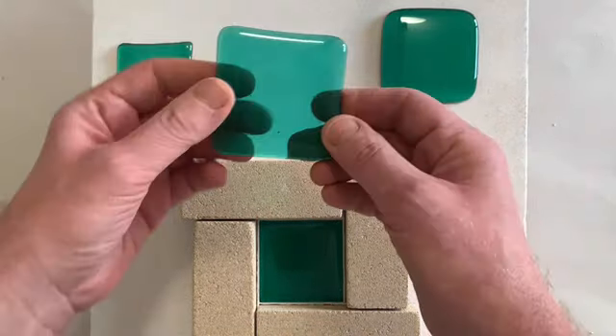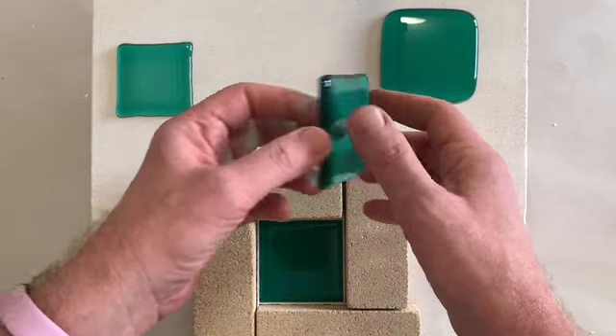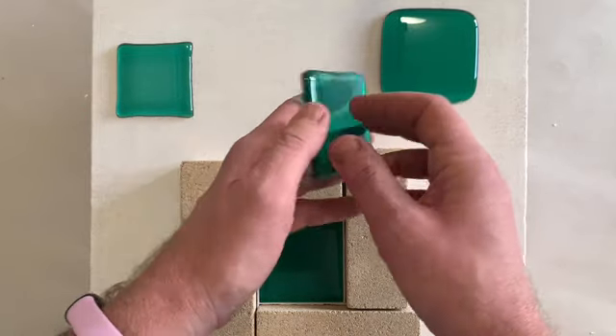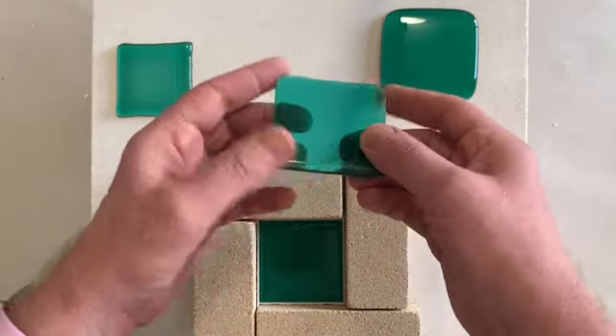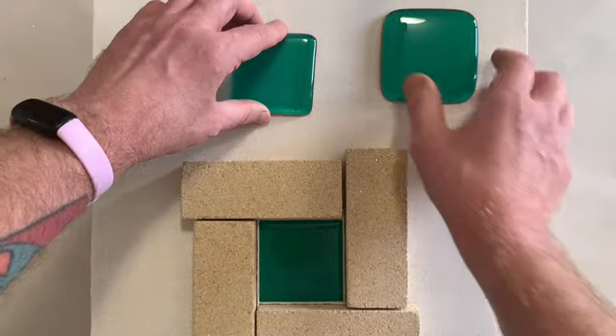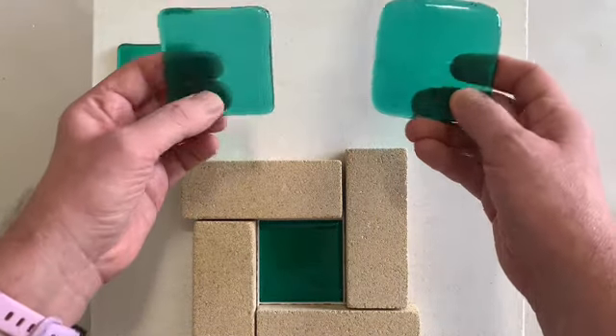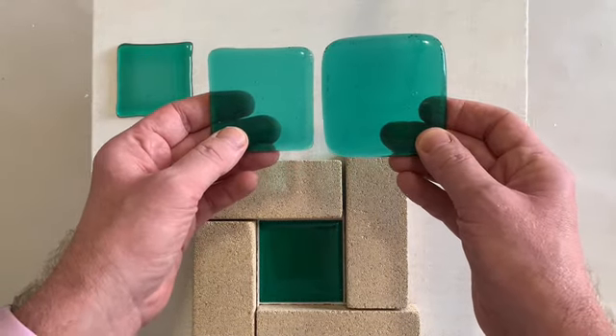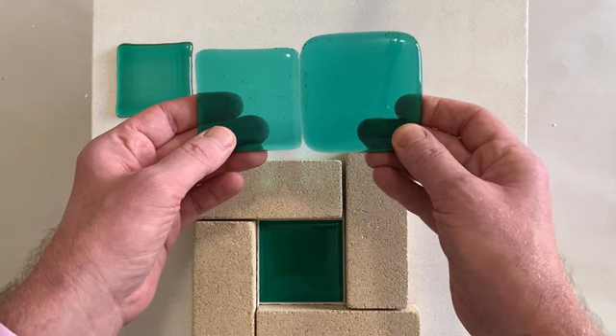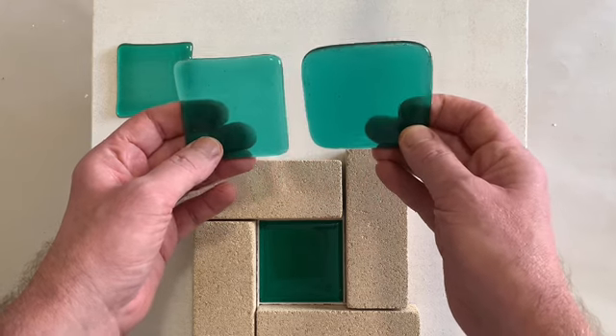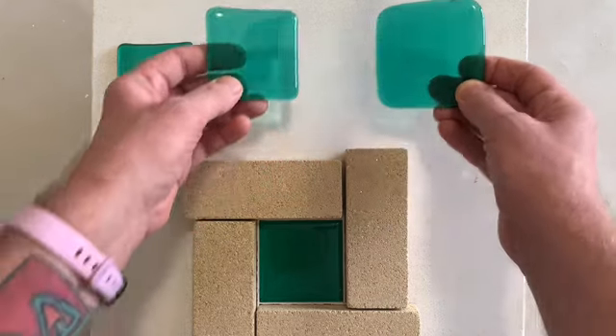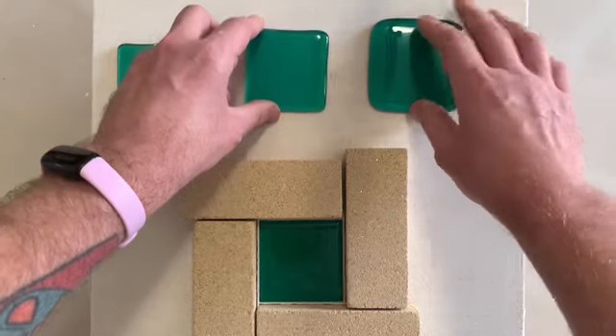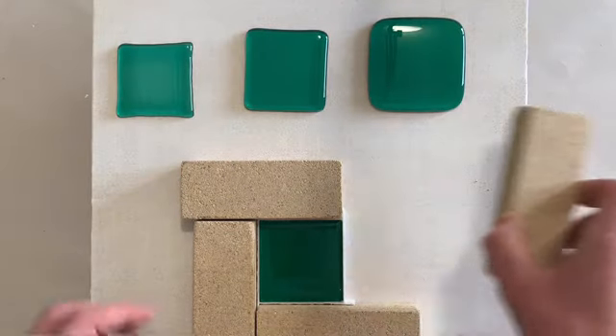The second sample is a standard 6 millimeter full fuse. It maintains its original shape and has a nice rounded edge. The third sample is 9 millimeters thick. Notice how only one extra layer of glass causes a great deal of flow in the final result. The glass flows out in all directions to assume a 6 millimeter thickness.